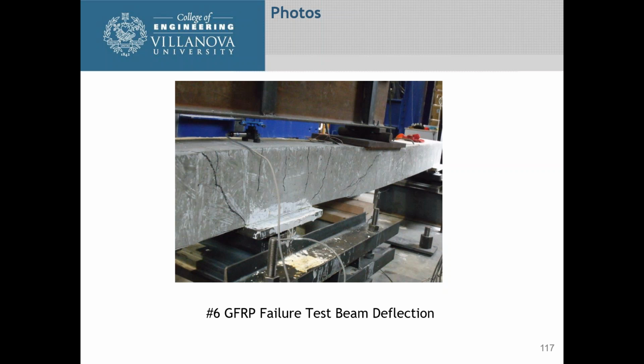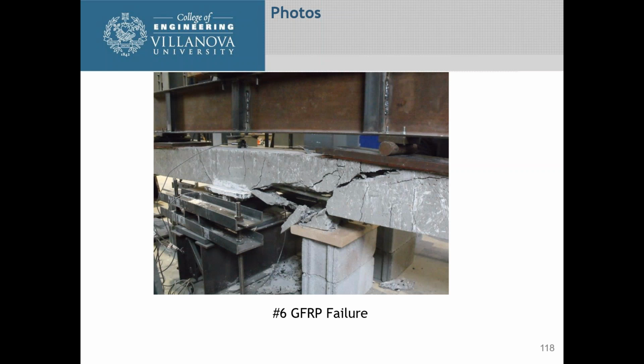Now you can see this is a number 6 GFRP beam, and you can see the crack patterns. Here's the diagonal cracking, and you can also see some of the curvature this beam is under due to the loads. Now, this is one of the failures that we got, and you can see that it's a shear failure from here up to where the load is. The GFRP bars never failed. It was the concrete that failed, but it didn't fail really in compression, it failed more in shear.